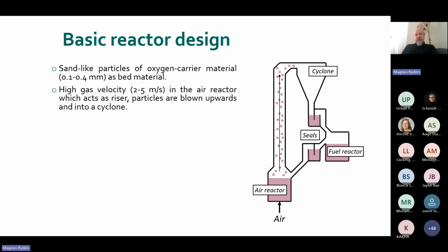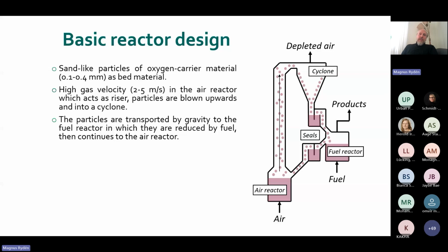The air reactor part we fluidize with high gas velocities, 2 to 5 meters per second. This means that we will actually blow these sand-like particles upwards. So this will act as what we in fluidization call a riser. These particles are then captured in the cyclone and transferred downwards in the system simply by gravity to the fuel reactor, where we are reducing it with our fuel. The loop seals in between the reactor parts work essentially as the water seal in a toilet. It prevents gas leakage between the two reactor parts.